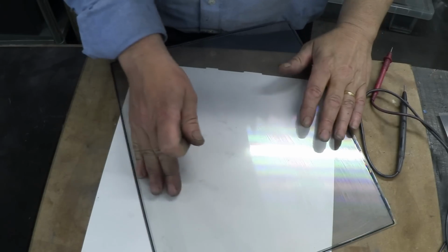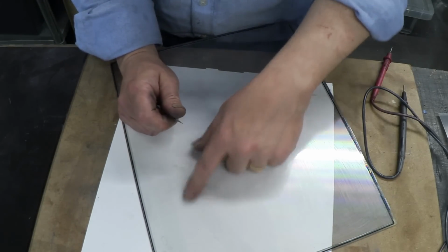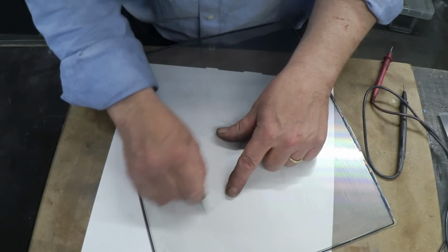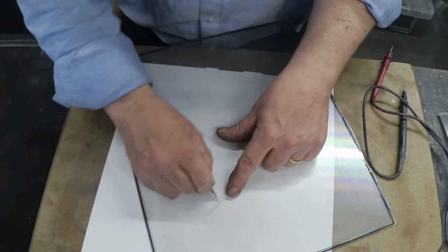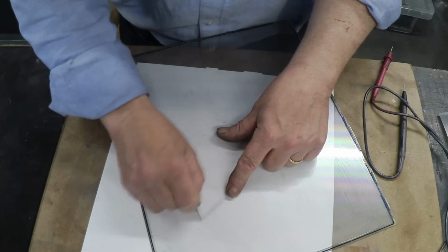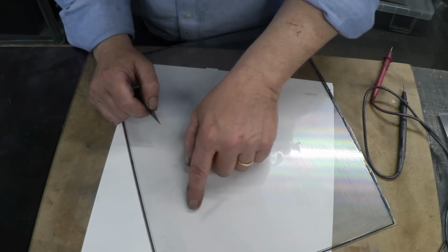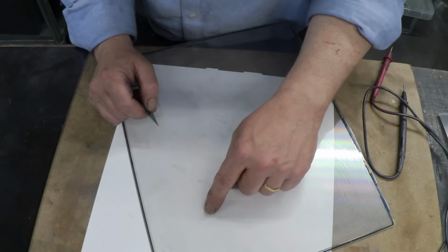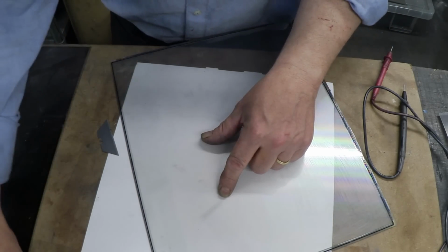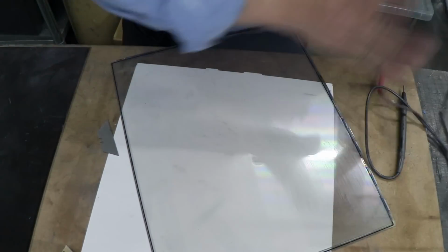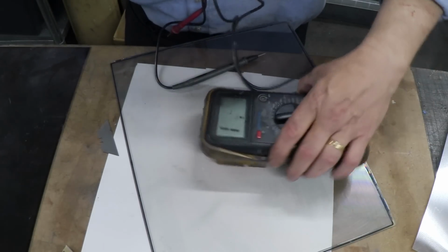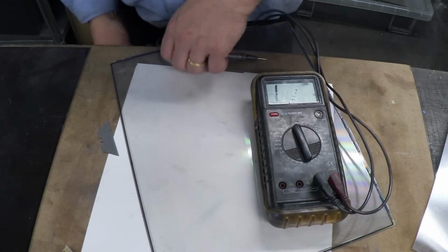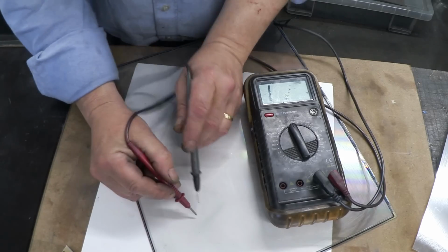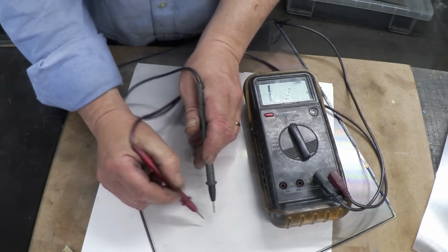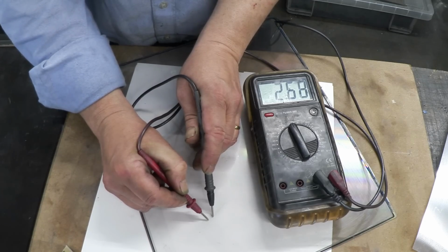Okay, I've put it on a white background because I'm hoping this will show up for you. That bit I haven't even touched. If I take my blade, you can see the polyimide coming off as those dark spots, and we've got a change in the colour there. Now, once we get that little bit off, you can use a fine grade sandpaper and even that out, and then we can check the conductivity. So on the bit next to it, as you can see, it's very resistive, and on that bit there, it's now conductive.